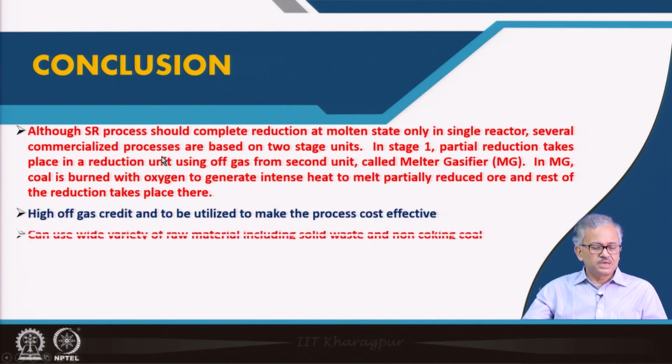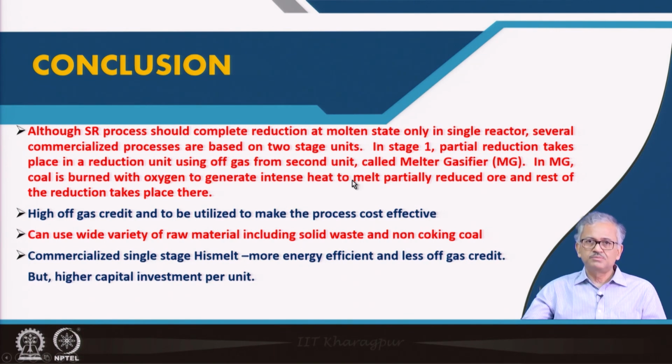And this process is basically a two-stage process, because initially the SR process was conceived as a single stage, or it can be a two-stage process. In a two-stage process you can utilize the gas a little more effectively. That's why in the two-stage process the efficiency becomes a little higher, but single-stage processes also come out to be very fine, especially the Hismelt process which is commercialized also. Its off gas credit is also less, the hot metal quality is excellent, and you can use any kind of raw material in the Hismelt process.